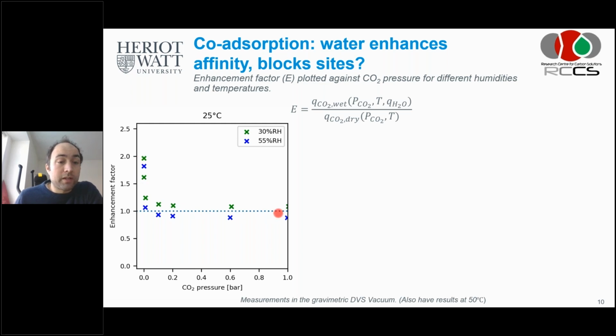What you also see is that it completely flattens out and goes to about 1, so no additional uptake at higher partial pressures. That is also beneficial because when you want to adsorb CO2, you also need to desorb it from your sorbent. That happens in an environment where you don't have much, if any, nitrogen or other air components. So your partial pressure of CO2 will be quite a lot higher than 400 ppm, something around 0.2 or 0.3 bar perhaps, and then you don't have an enhancement. That's beneficial, so the thermodynamics work in our favor in that respect.